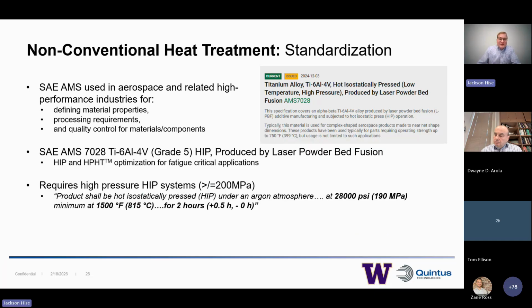One thing that's interesting in the last year or two is the standardization of this optimized HIP parameter. SAE AMS is used in the aerospace and high-performance industries, as I'm sure many of you know. AMS 7028 calls out Ti-6Al-4V laser powder bed fusion components and the HIP process required. This is an alternate to the traditional cast variant, as we have higher pressure, 190 MPa compared to 100 MPa, at 815 degrees C, so that lower temperature.